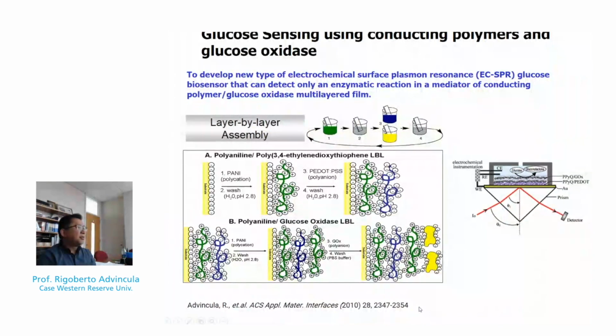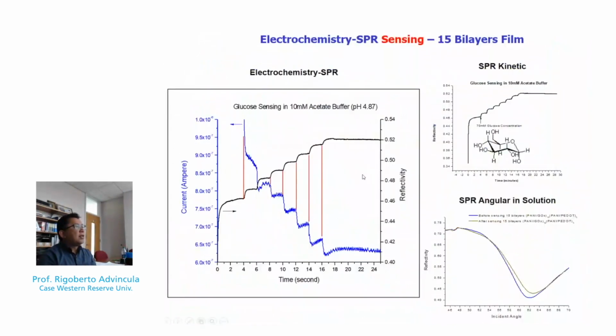Actually, this reference here refers to another paper. But what we have is this sensitive layer or dielectric nanostructured layer on top of a gold surface that serves as the SPR coupling for production of that evanescent wave. So if you do that, one can monitor the deposition of the film. One can also monitor the redox cycle. One can monitor the change in potential or current simultaneously with the reflectivity changes. So as you can see here, by conducting an electrochemistry SPR deposition on that sensing layer, we can have both data, reflectivity and current, as a function of time, which is very useful for monitoring both the deposition and redox properties of the sensing element.